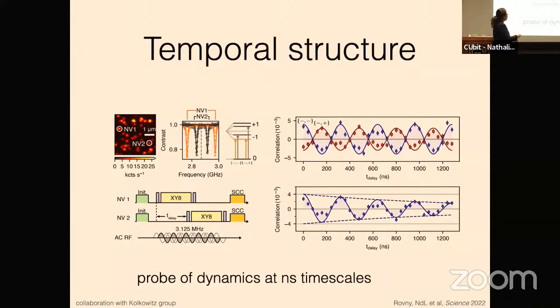And then similarly, I can use this as a probe of dynamics at these timescales. So now if I really randomize, if I add some noise to this phase so that the phase noise destroys your coherence in under a microsecond, this is not something that you would normally be able to see with an NV center because the total overhead of your sequence is something like 10 to 20 microseconds. But now, because I can just sort of set the time delay arbitrarily between these two NV centers, I can see this dephasing on these very short timescales.